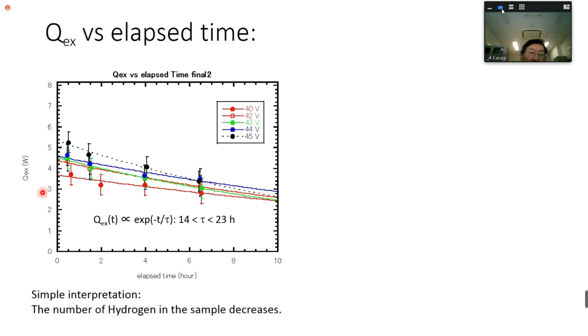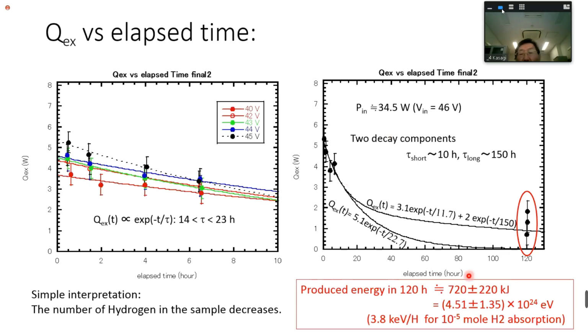But this excess heat variation just depends on the elapsed time of the experiment. If you put the various data in this way, this is just going down, as if the decay of the reaction rate. The simple interpretation is the number of hydrogen in the sample decreases, then the reaction rate decreases. But if you continue to, for example, 120 hours, about 5 days, there's still excess heat over here. So we think this is just a 2 decay component.